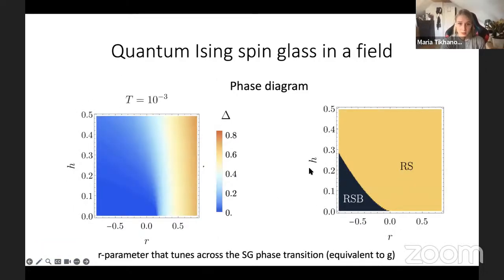Okay, the phase diagram is the following. We fix the temperature. It's pretty small, but it's non-zero. That's important. This H is the longitudinal field, and R is just the parameter in the Landau theory. So first of all, we study the Landau theory of this model. This R is the parameter in Landau theory that makes you go from one phase to another phase. And we measure the gap in this case, and we see that the model becomes gapless in quite a large regime, and then the gap grows, right? And this is the actual phase diagram.